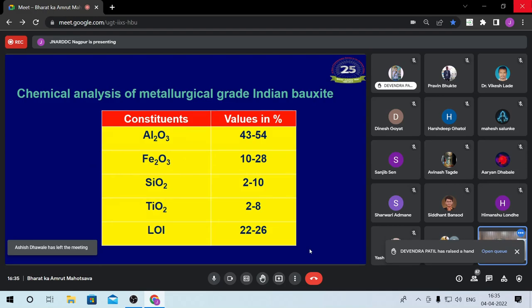For using the bauxite, the bauxite should have the following characteristics. The alumina should be in the range of 43 to 54%, iron 10 to 28%, silica 2 to 10%. But normally the aluminium industries prefer that the silica should be less than 4% or 5%, because higher silica concentration will result in more caustic soda losses, and titanium dioxide and loss on ignition. Loss on ignition is the crystalline water which gets out when you heat the bauxite to a temperature of 1100 degrees. So these are the general characteristics of metallurgical grade Indian bauxite, and luckily for us, India being the fifth largest producer of bauxite, the quality of the bauxite available in the East Coast part is excellent for alumina production, that is for metallurgical grade.